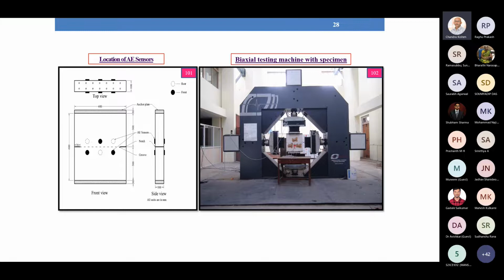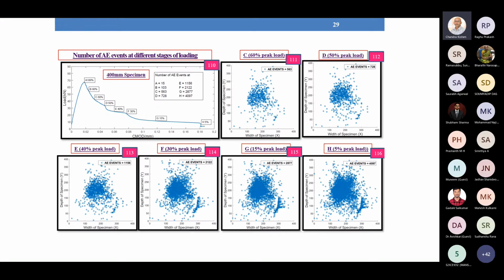Because of gripping the specimen at the grips, the failure takes place there and we will not get a complete softening response. So in this case, we have put a steel plate with threaded holes matching the holes on the machine. This is done at the time of casting itself, and after the specimen is cured for 28 days, the specimen is fixed through bolts. So there is a bolting arrangement to fix the actuator to the specimen. Let me show you some results. This is the typical softening response.